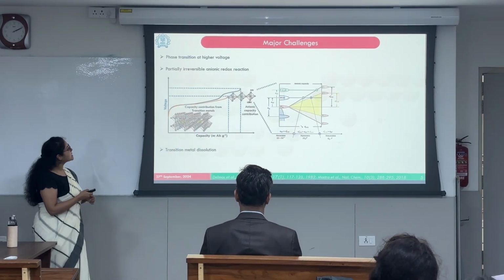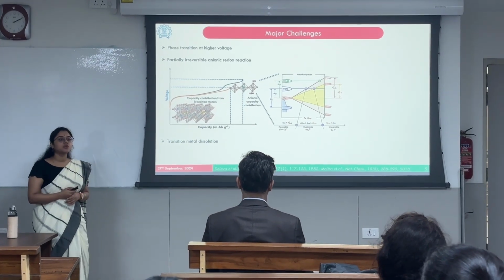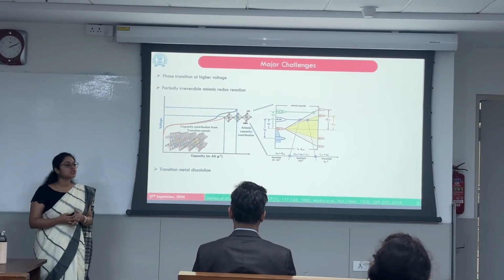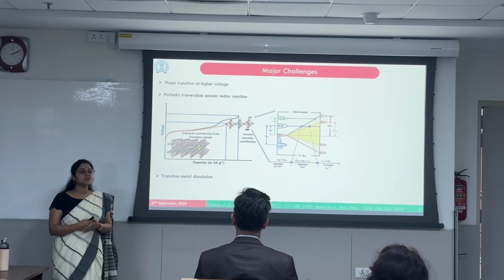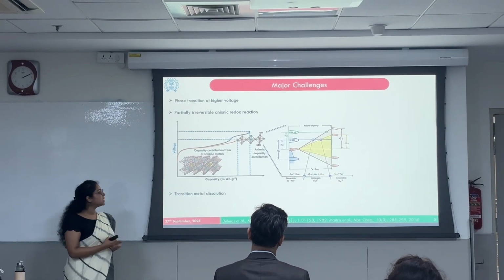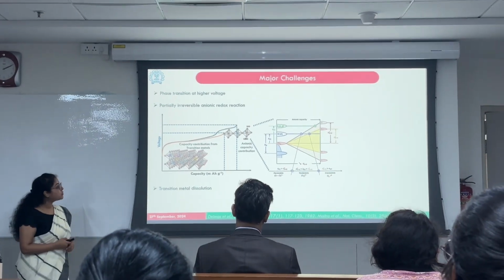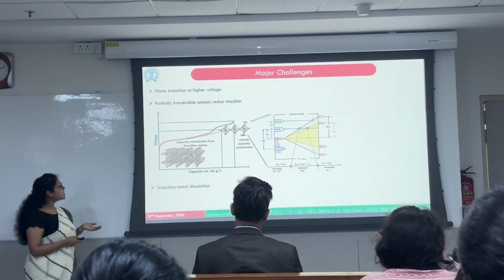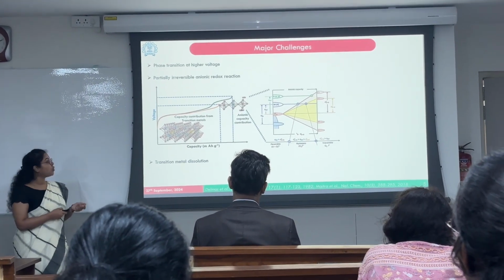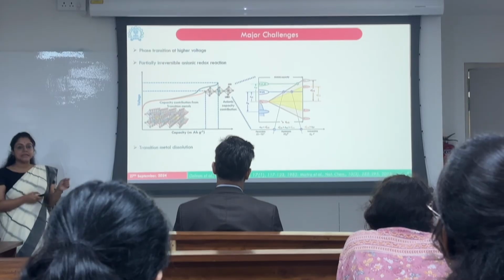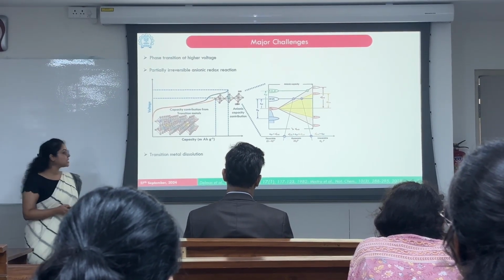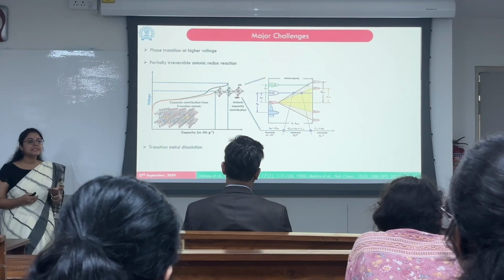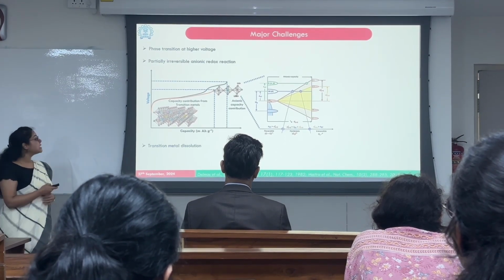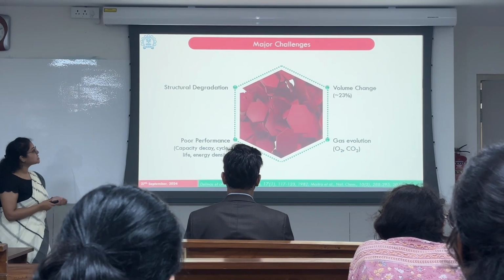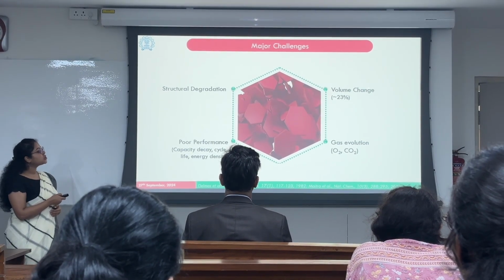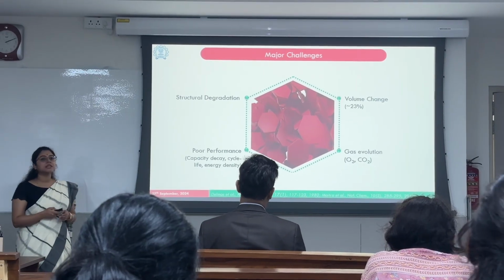Another problem is the partial irreversibility of anionic redox reaction. Although anionic redox reaction has been a boon for the sodium-ion cathode material, which can make it complementary to that of the lithium-ion battery cathode materials, however, it comes with its own sacrifices. The first and foremost being the irreversible capacity loss because of the loss of oxygen from the lattice, leading to structural distortions. Another problem when we try to activate the manganese in the cathode material is transition metal dissolution. This leads to consequences such as structural degradation, volume change, gas evolution, and poor electrochemical performance.